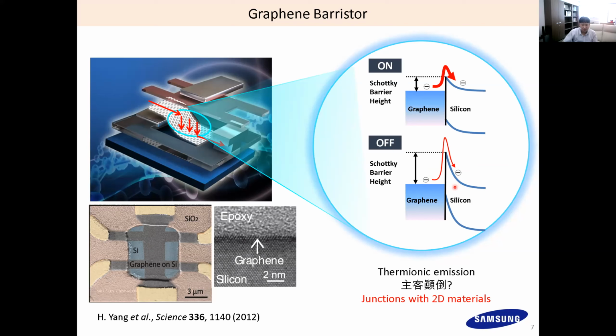So if we think about the tunneling process, what about modulating the tunneling barrier height? That was my question. For example, for the on state, we have a low Schottky barrier height, and for the off state, we may use a high Schottky barrier height. That means we use thermionic emission. Like this. But we have many issues, and in the graphene barristor case, I solved this problem in some primitive way.